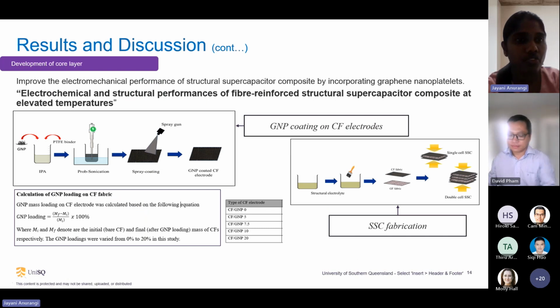My second objective was to improve the electromechanical performance of the structural supercapacitor composite by incorporating graphene nanoplatelets. Actually, these findings were presented in the journal article titled Electrochemical and Structural Performances of Fiber Reinforced Structural Supercapacitor Composite at Elevated Temperatures. In this project, I use graphene nanoplatelet coated carbon fiber fabric as the electrode. I prepared the GNP coated carbon fiber fabric like this.